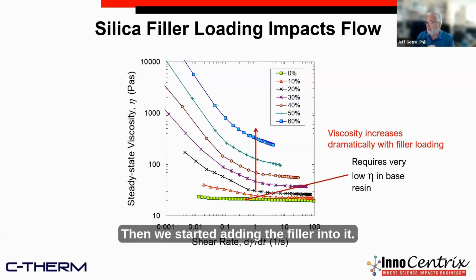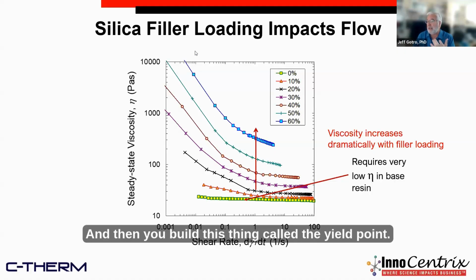Then we started adding the filler into it. Then you start getting this viscosity increase, and this is on a log scale. So once you get up to 60 volume percent filler in silica, the viscosity is really big. And then you build this thing called the yield point.